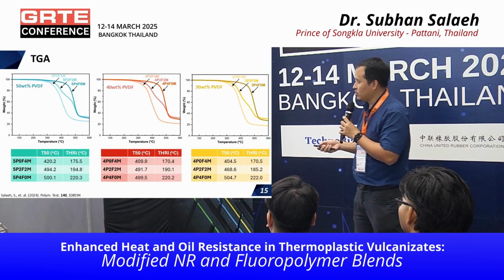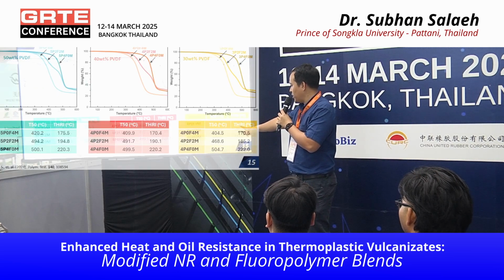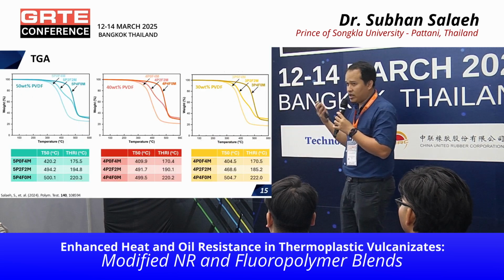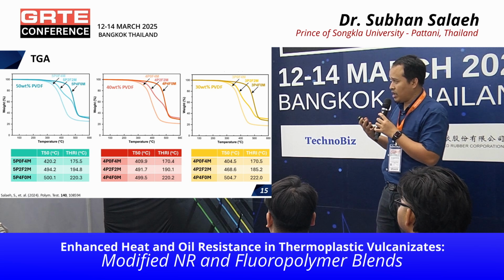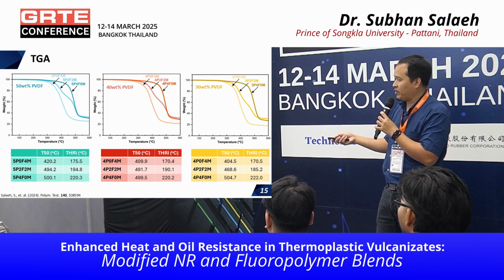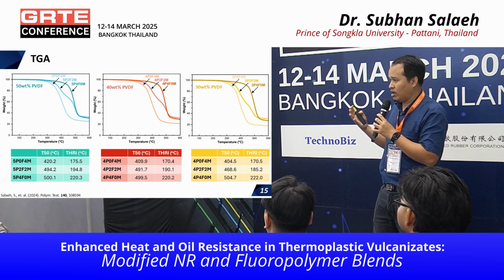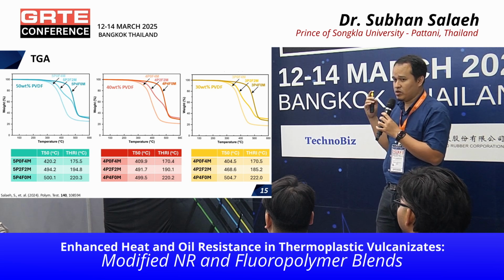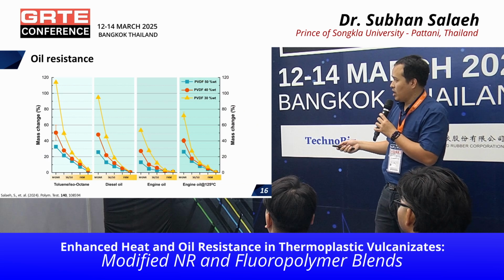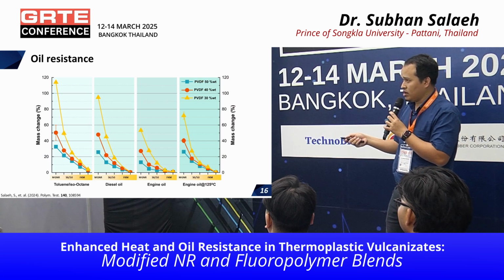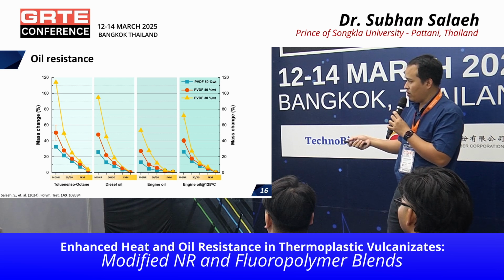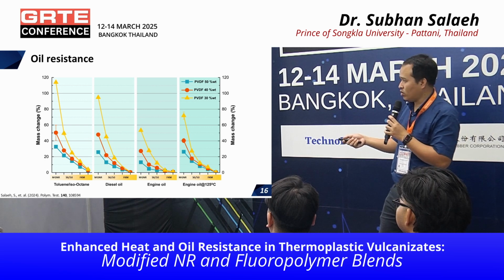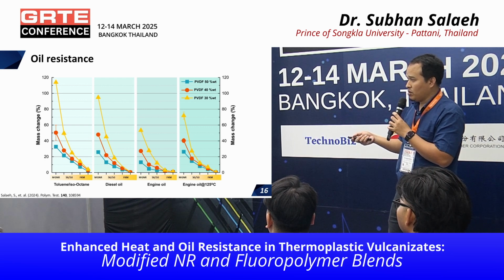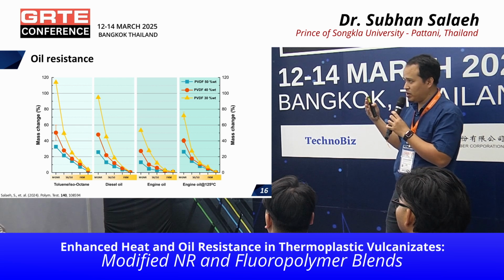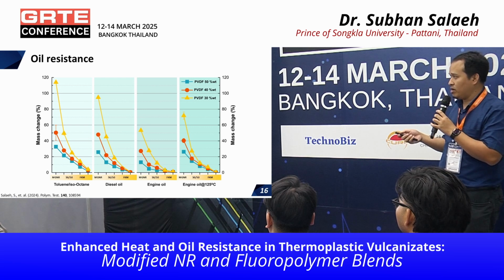And this is the heat resistance. We can see here in this table that with increasing FKM, we increase the onset temperature and the temperature at 50% loss. So with increased FKM, that means we can improve the heat resistance of TPV by adding FKM into the TPV. And also we can see that the oil resistance is better when we increase the amount of FKM and PVDF. This TPV shows small swelling in toluene, diesel, and engine oil, even at high temperature. So it means that we can improve the TPV by adding FKM and PVDF.